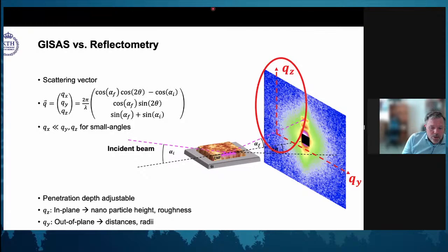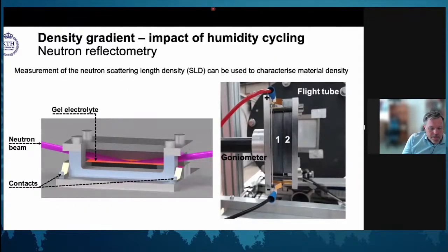And by doing neutron reflectometry, we will actually try to understand what happens through the thickness of the film. Because then we get something called the neutron scattering length density as a function of our measurement, and that can characterize the density of the material, the amount of material throughout the sheet.